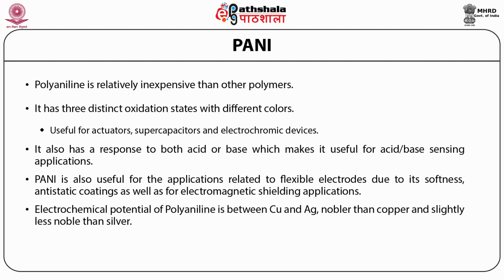The unique aspect of polyaniline emerges upon the exposure of the EB state, or emeraldine oxidation state, to strong acid, inducing the formation of the green emeraldine salt form of polyaniline. This form exhibits electrical conductivity up to 10 orders of magnitude higher than its unprotonated counterpart.